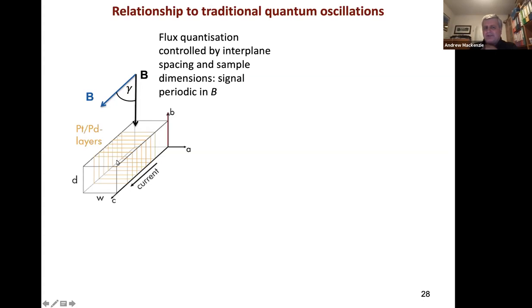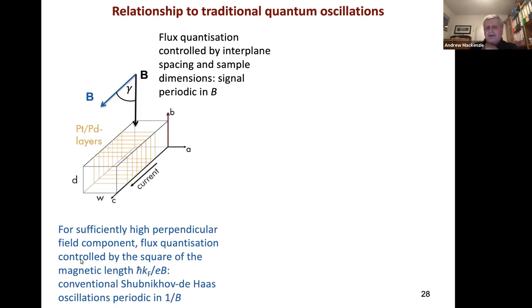So by the time you've reached that point, you're just in the basic physics like the Shubnikov-de Haas effect, and the same flux quantization ideas based on a real space orbit, that is now flux quantization controlled by an area which is the square of the cyclotron radius or magnetic length. And that magnetic length goes as 1 over B, so the area goes as 1 over B squared. So there's a very neat way of seeing why, if they were Aharonov-Bohm oscillations, which they probably aren't, Aharonov-Bohm oscillations are periodic in field, whereas Shubnikov-de Haas oscillations are periodic in reciprocal field.